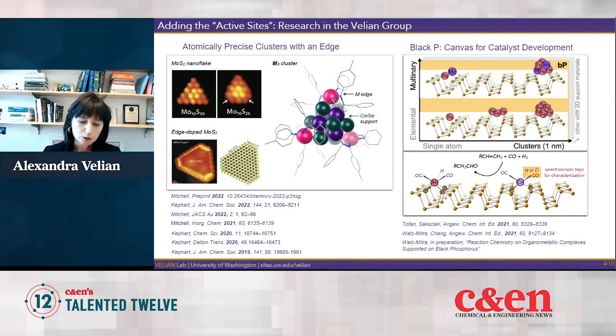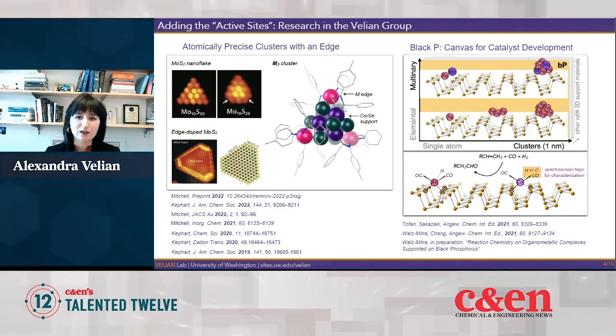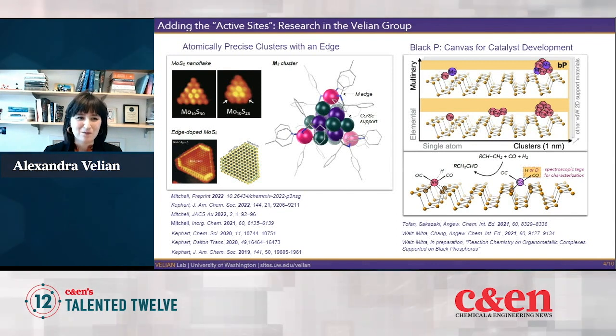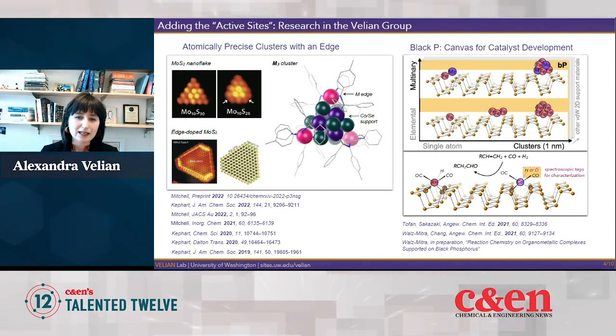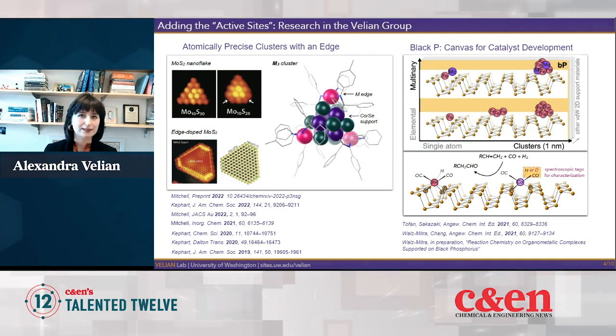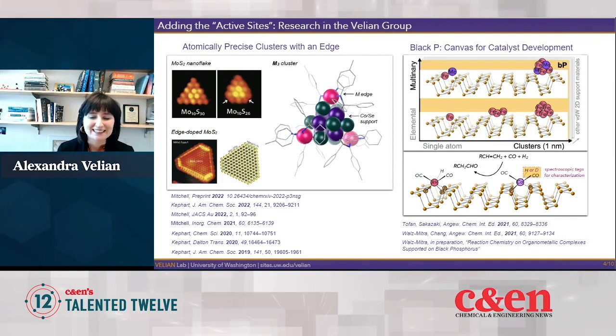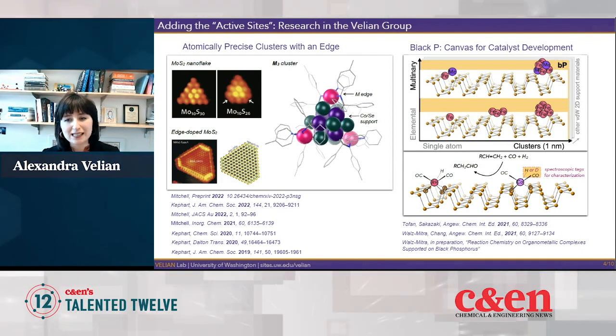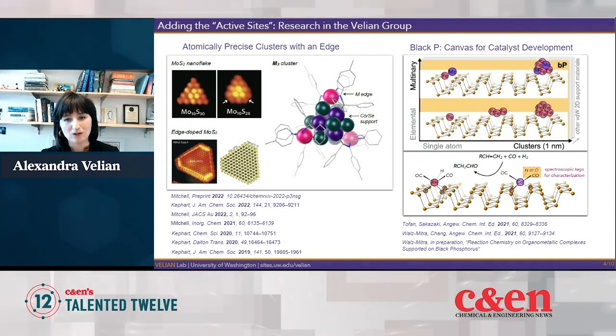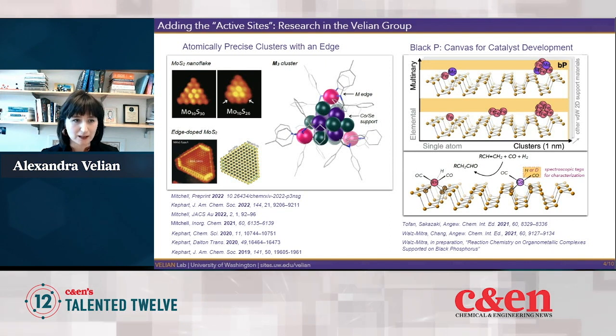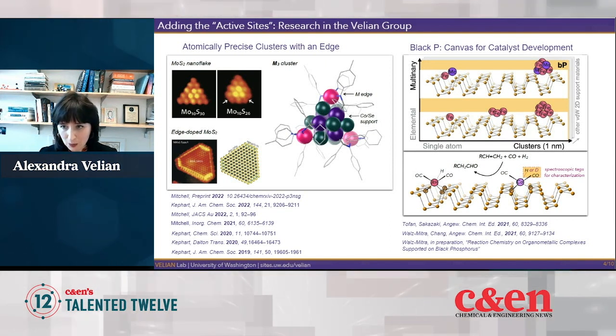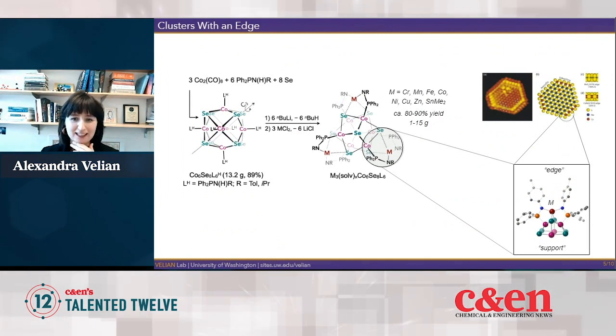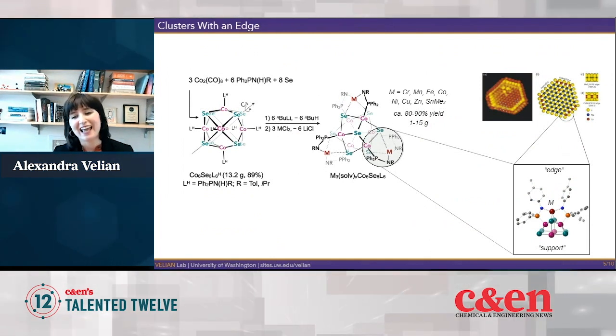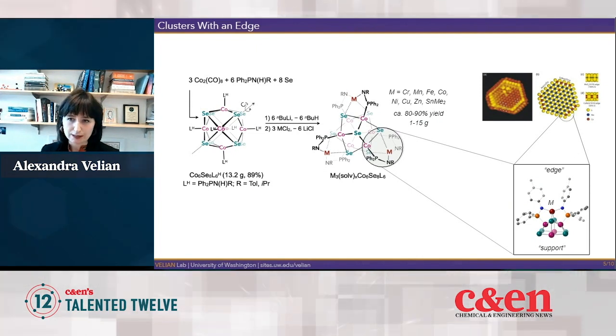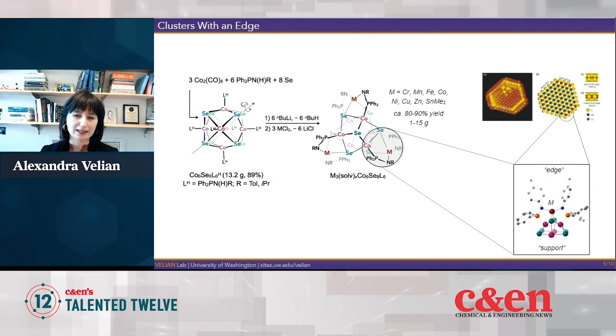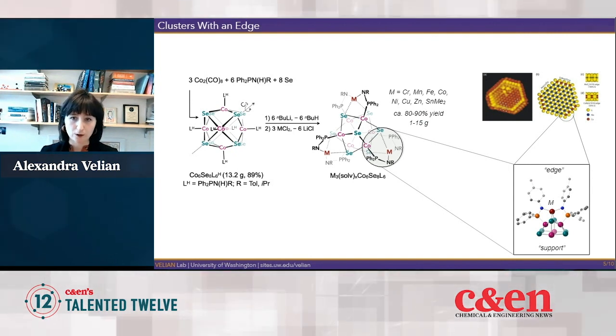But in an orthogonal approach, we also take a more molecular path by creating these atomically precise clusters that encompass some complexities of a surface, and that importantly feature these three edge sites, or so-called active sites on their surface. And I'll tell you a little bit about that now. So these clusters, again, have an edge, three in fact, and these are really critical to their activity. Let me tell you a little bit about how we prepare them, because this is really central to a lot of the work we've done thus far in the group.